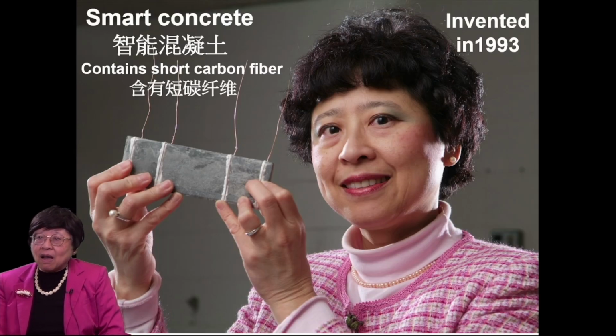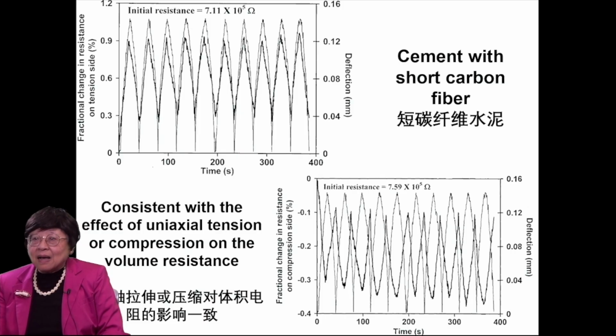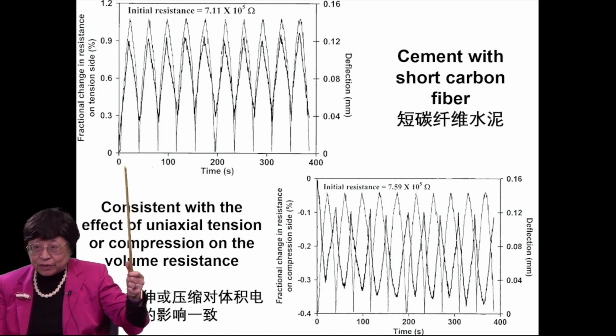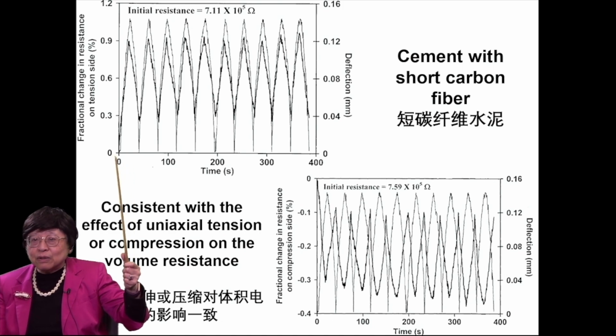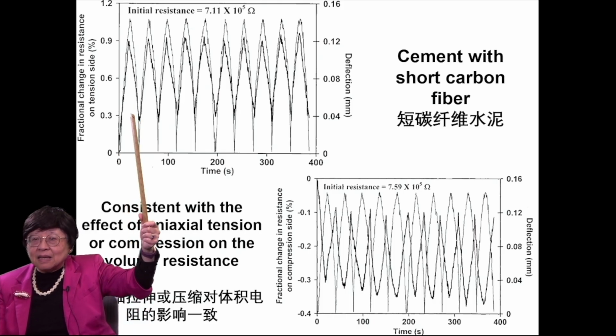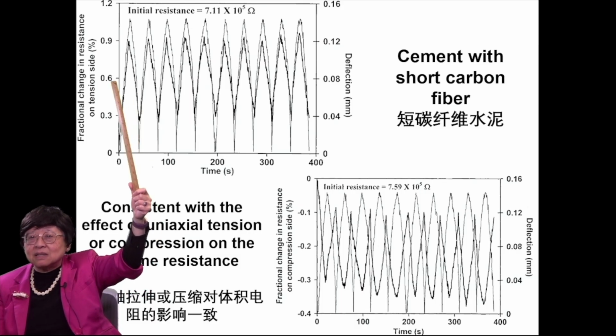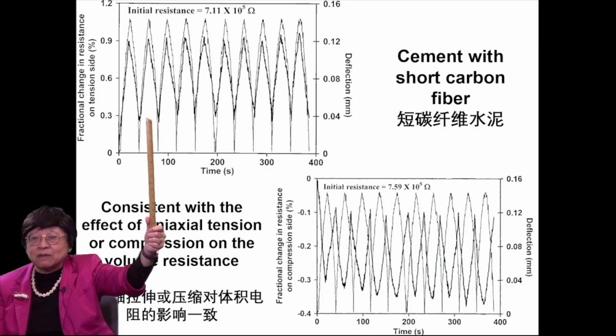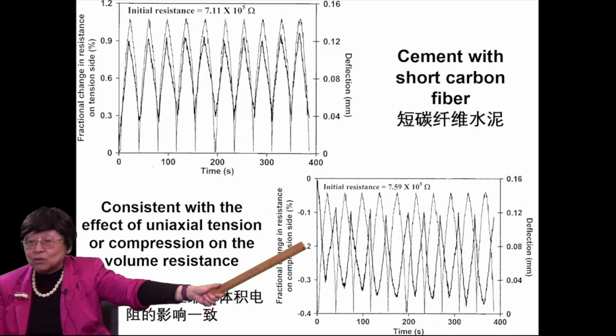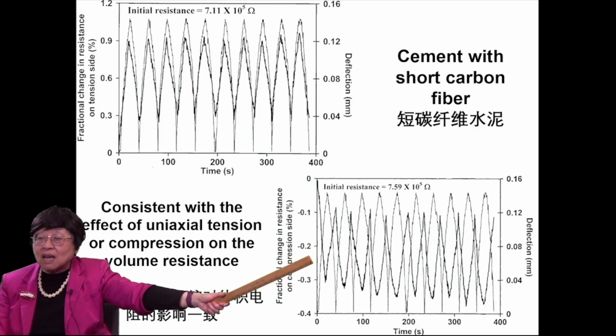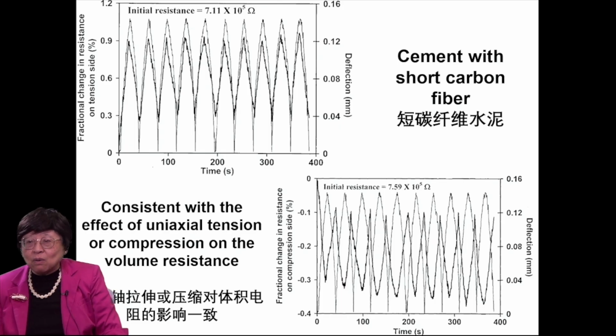I invented smart concrete back in 1993. It contains a small amount of short carbon fiber. And this is the result of that cement with short carbon fiber under flexure, again using surface resistance measurement. And again, we see that on the tension side, the surface resistance increases every time one flexes, and the surface resistance on the compression side decreases every time one flexes.